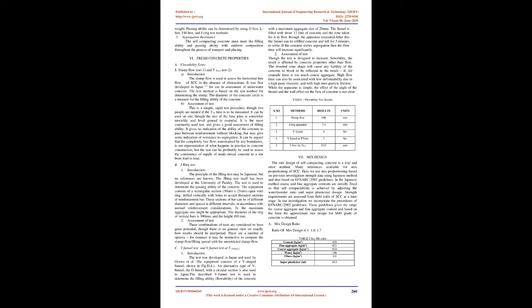After conducting the flow characteristic experiments, the concrete mix was poured in the molds required for the strength assessment. After pouring the concrete in the molds, no compaction was given, either through vibration or through hand compaction. Even the concrete did not require any finishing operation. After 24 hours of casting, the specimens were demolded and transferred to the curing tank, wherein they were allowed to cure for 28 days.